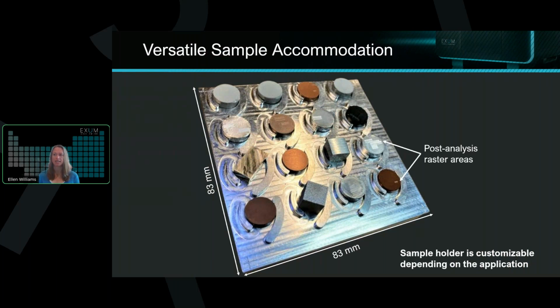Again, just because of the fact that we can analyze anything and get the full periodic table, and because we don't have to be tuning or searching for specific elements with the time of flight, it would allow you to get really, really quick feedback. Again, I mentioned as little as 15 minutes for just a quick scan to verify the chemical composition. Obviously longer if we're doing a larger elemental map, but I think this technique would be well suited for the experimental pieces needed to validate an ICME workflow. And so we would definitely be open to discussing something like that.